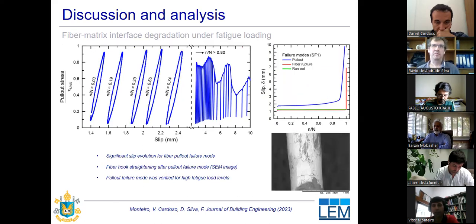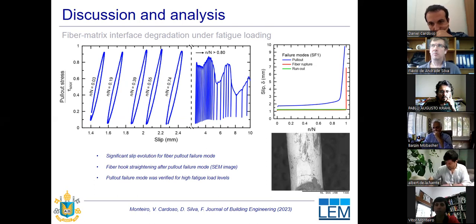So here we have to see how the pull-out failure happened. It was possible to verify a significant evolution of the slip. For the pull-out failure, we can see here at the blue curve, it has a slip evolution. And for this kind of failure, we could verify that the hook of the fiber presents a straightening after the pull-out. So during the degradation of the interface, this hook is being straightened along the fatigue life until it is completely pulled from the dog bone specimen.